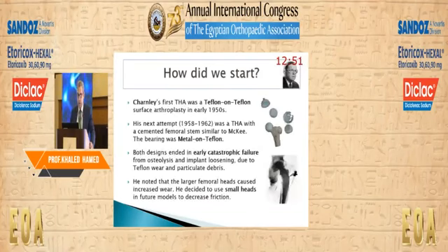Sir John Charnley did his first attempt at total hip arthroplasty using Teflon on Teflon in the 1950s. His next attempt was metal on Teflon, but both structures failed catastrophically because of early osteolysis and loosening, because of the wear particles of Teflon. So he noted also that larger femoral heads caused increased wear. So he decided to use small heads in order to decrease friction.